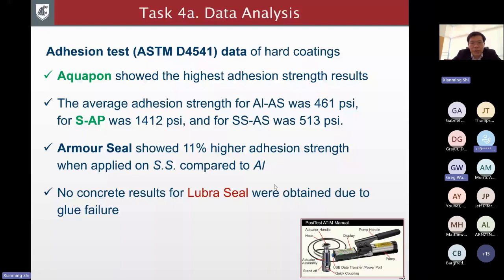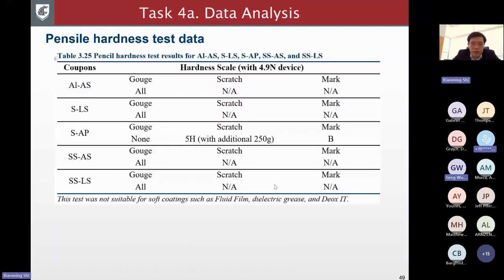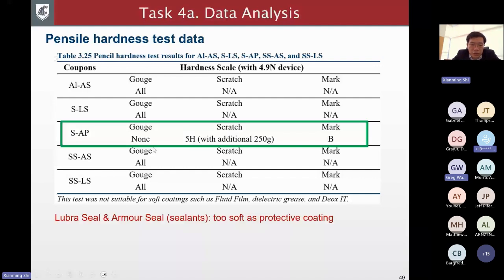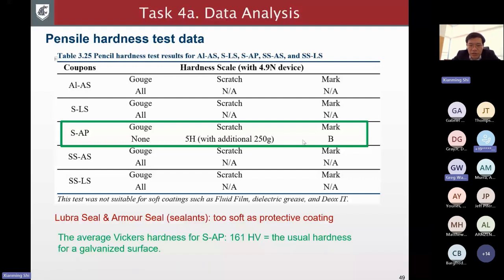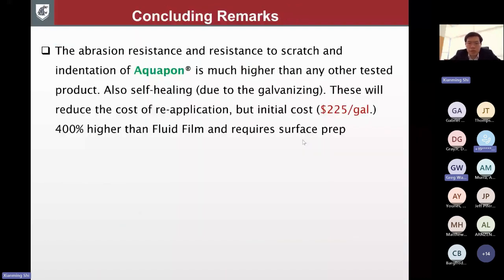Now, in terms of the pencil hardness test, the vast majority of the coatings were just too soft. The only exception was this sacrificial anode, whose brand name is Aquapon, a zinc-rich epoxy primer that is sufficiently hard. In fact, we had to add additional load to be able to measure its hardness with the pencil hardness test. Otherwise, it would be too hard to measure. And again, this is no surprise because this is a very zinc-rich primer, so its hardness is similar to a galvanized surface. To conclude, the abrasion resistance and resistance to scratch and indentation of Aquapon is much higher than any other tested product.